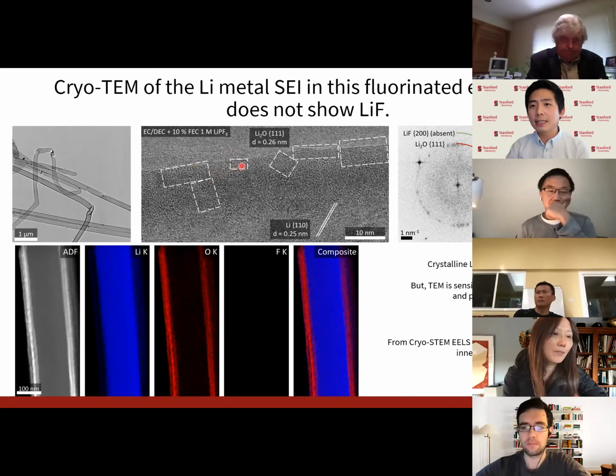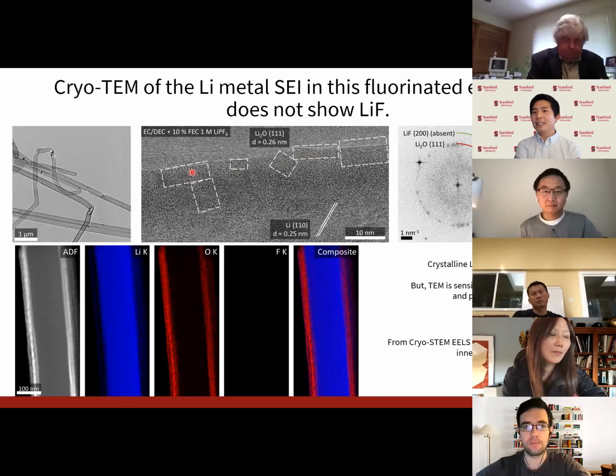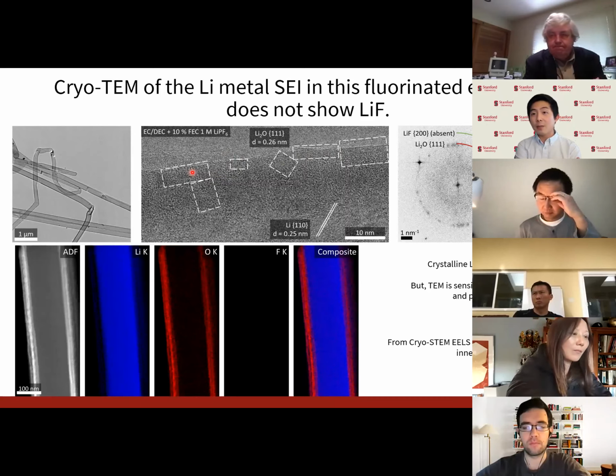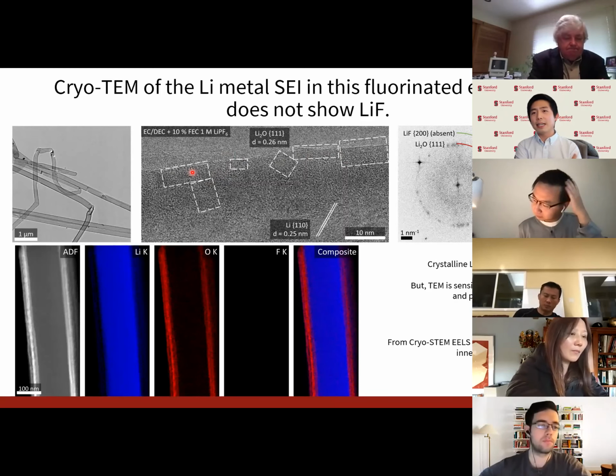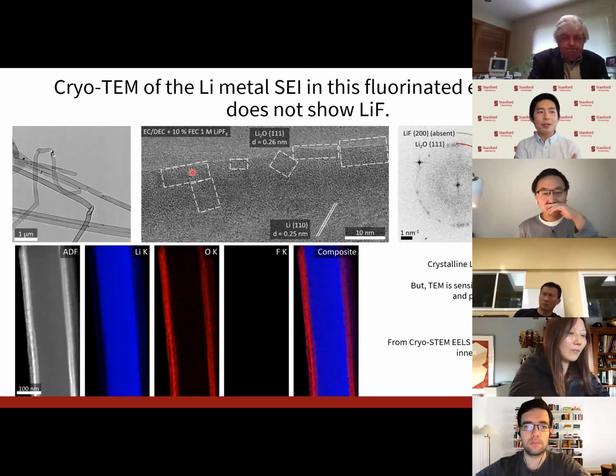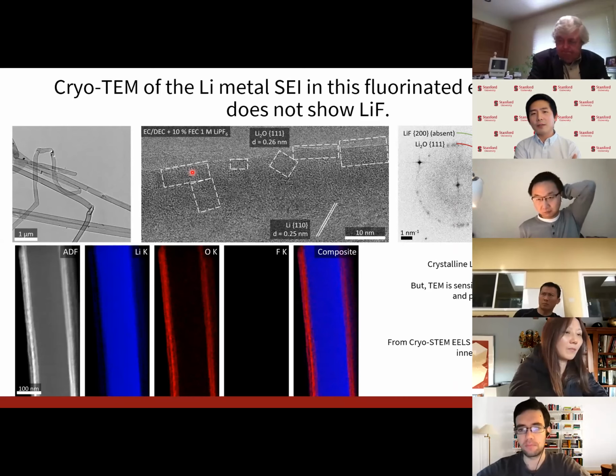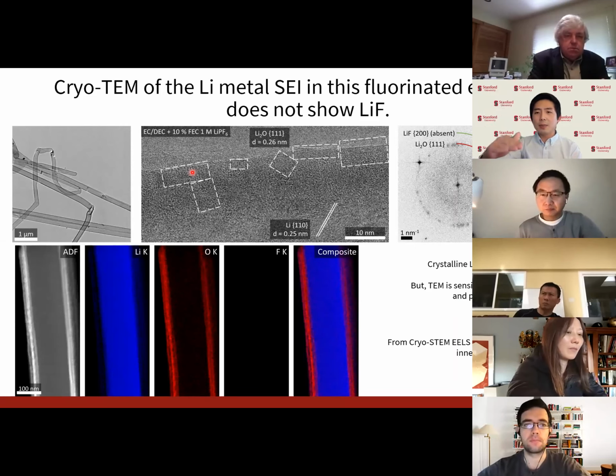And that's because in the silicon study, we can see lithium oxide only when there's no FEC. So the difference then comes from the potentials that lithium metal sees and a fully lithiated silicon anode sees when it's lithiated down to 10 millivolts, which are about the same. It's about 0 volts versus lithium versus 10 millivolts versus lithium. That's a 10 millivolt difference, so it's likely not due to the reduction potential. I think the main difference is that when you are forming an SEI on any lithium ion battery system, whether it's graphite or silicon, you're bringing down the potential of the surface in a controlled manner, so somewhat slowly. During formation, you would do this at maybe 1/20th of the nominal electrode capacity. So you're basically sweeping the potential from open circuit down to the lithium potential very slowly.